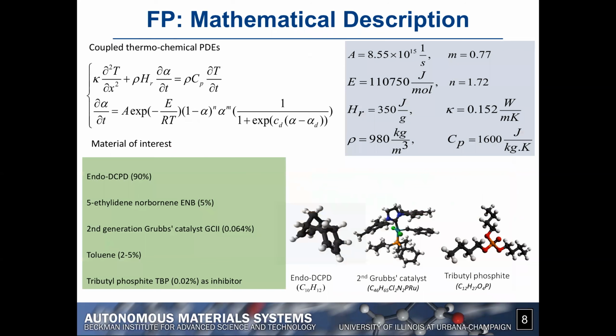Now, from a modeling perspective, the way we describe the system is using the coupled partial differential equations you can see on the top left, which are written in terms of the temperature, capital T, and alpha, the degree of cure. The degree of cure is a quantity that captures the evolution of the material during the polymerization. Alpha equals 0 is the monomer, alpha equals 1 is the fully polymerized polymer. And the coupling is associated with the term rho H_R d alpha/dt, which corresponds to the heat generation associated with the exothermic reaction.